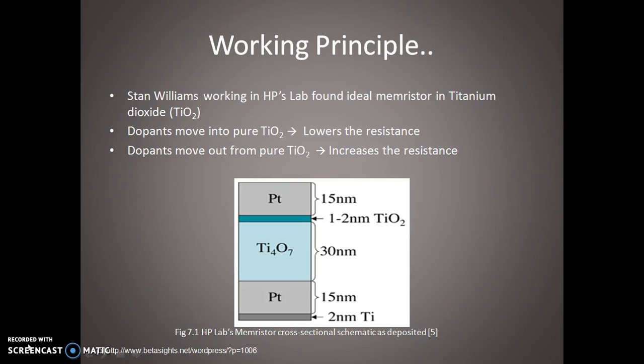R. Stanley Williams found an ideal memristor in titanium dioxide. Like silicon, titanium dioxide is a semiconductor and in its pure state, it is highly resistive. However, it can be doped with other elements to make it very conductive. In TiO2, the dopants don't stay stationary in a high electric field. They tend to drift in the direction of the current. Putting a bias voltage across a thin film of titanium dioxide semiconductor that has dopants only on one side causes them to move into the pure TiO2 on the other side and thus lowers the resistance. Running current in the other direction will then push the dopants back into place, increasing the TiO2's resistance.